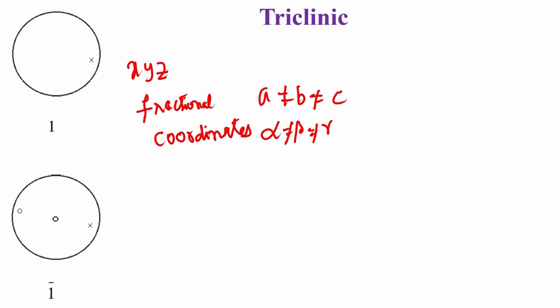So, these are referred to as fractional values of a, b and c. Normally the x value will appear as, let us say, 0.1, which means it is 0.1 of the distance a or the length a. So, the fractional coordinates are representations of the 3-dimensional coordinate system in the given crystal system. So, if the system is triclinic, we have this way of representation, that is to see that x, y and z now represent fractions of a, fractions of b and fractions of c.